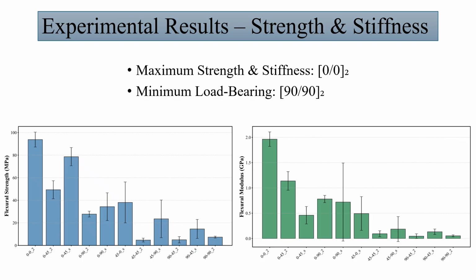When we convert that data into material properties, the trend is undeniable. As seen in the blue bar chart for flexural strength and the green chart for flexural modulus, the 0-degree laminate exhibited the highest performance, as the fibers were perfectly aligned with the principal bending stresses. The 90-degree laminate showed the lowest load-bearing capacity, relying entirely on the much weaker polymer matrix. Interestingly, the hybrid and off-axis configurations displayed intermediate, predictable performance.